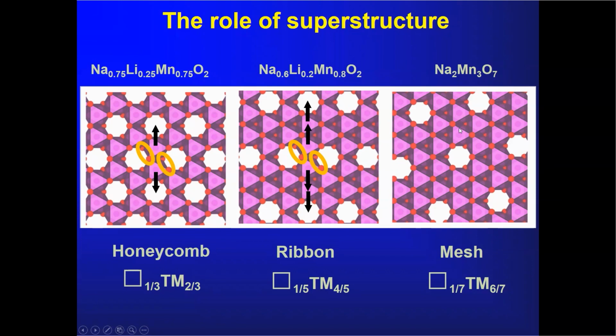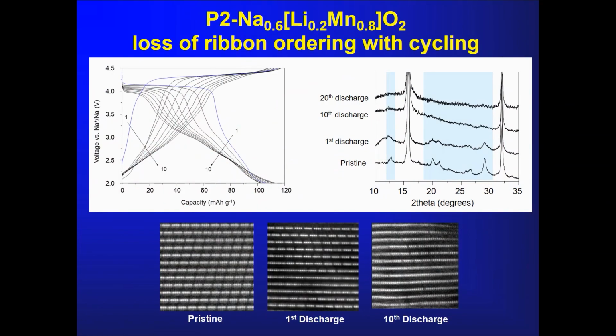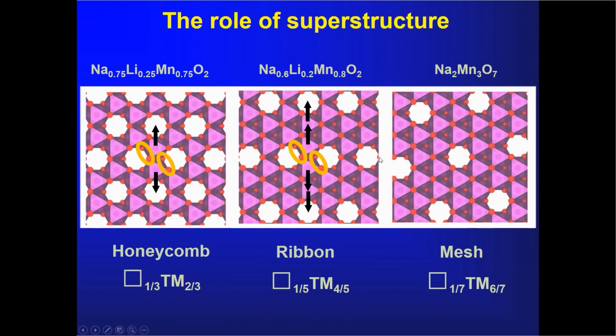And of course, in the mesh structure, you could see even more separation of lithium vacancies. It will become even more difficult for them to come together, requiring multiple manganese displacements. And this is in large measure the reason why you get suppression of molecular oxygen formation in the case of these other superstructures. So the superstructure on the transition metal layers can help to suppress molecular oxygen formation and trapping in the bulk.